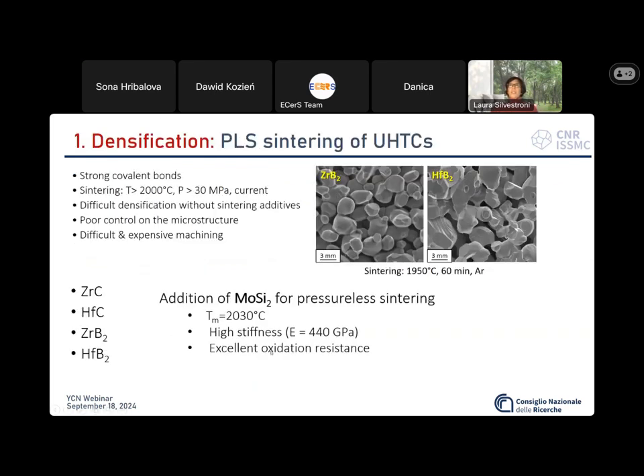So starting with the densification, you know that borides and carbides have strong covalent bonds, and therefore they require sintering temperature above 2000 degrees C, application of mechanical pressure, and even current. It is difficult to densify such pure borides and carbides without any sintering additive and control the microstructure, so as to obtain good performance. Furthermore, it is difficult to machine such strong materials.